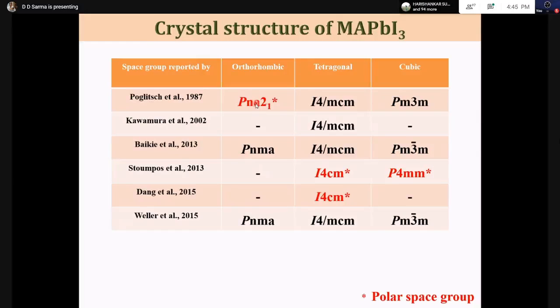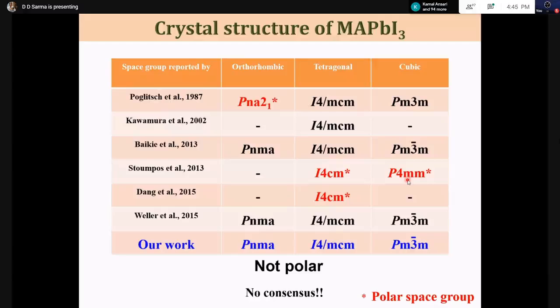And that means for any given structure, the low temperature structure, somebody says it's a polar structure, some say it's a non-polar structure. For the room temperature, important phase, tetragonal structure, some say it's a non-polar structure, some say it's a polar structure. Even for the cubic phase, some say it's non-polar and some say it's polar. So there was no agreement, and we looked at the single crystal X-ray diffraction very carefully, and we came to the conclusion that all of them are actually non-polar.